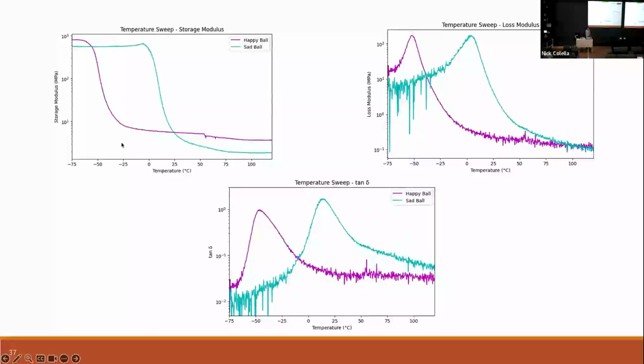We can then do a temperature sweep and say, okay, given just one amplitude and one frequency, we're going to sweep our temperature and see how the material responds as a function of temperature. So for the storage modulus, we see that above negative 40 degrees or so, the happy ball is pretty consistent, but below that, it becomes much stiffer. So what do you think this is? Thinking about the DSC data. So what type of transition? Okay. So this is our glass transition here. So it's in the rubbery state from about negative 25 and higher, and it's in a glassy state at negative 50 and lower. So if you cool that ball down, put it in liquid nitrogen for a while, it's going to be glassy like a ping pong ball.